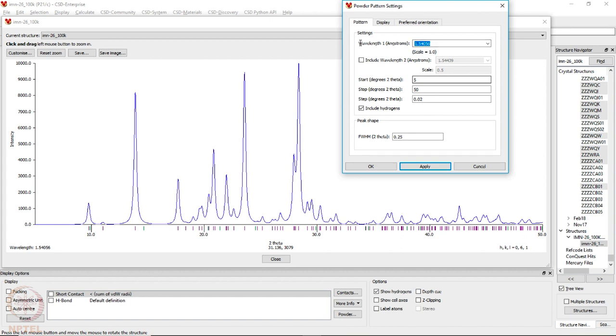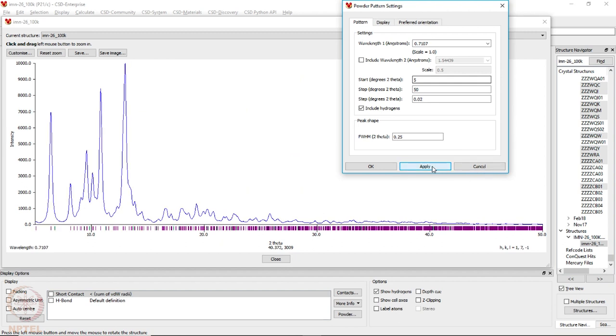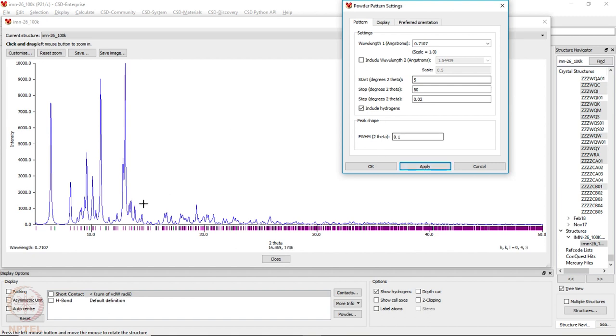Now if I change this wavelength to the molybdenum wavelength, which is 0.7107 angstrom, and apply, you see the entire pattern which was spread over a large 2 theta range is now squeezed. Most of the peaks have merged and it has become more featureless. Even if I make the FWHM 0.1, the peaks are very, very close and sort of merged. So, that is why we do not record any powder X-ray data using molybdenum.